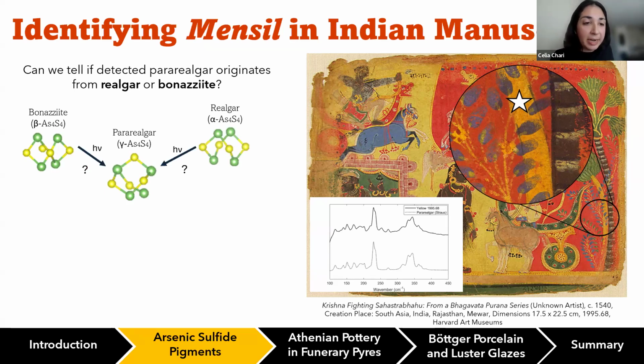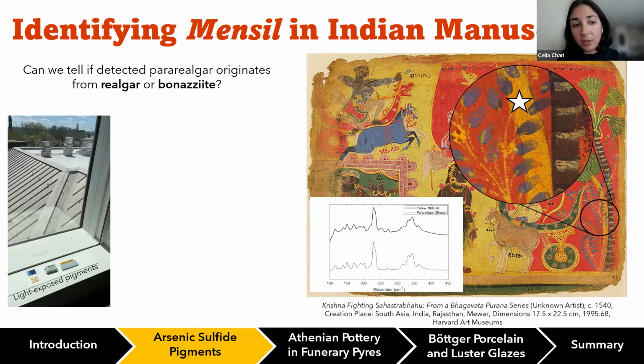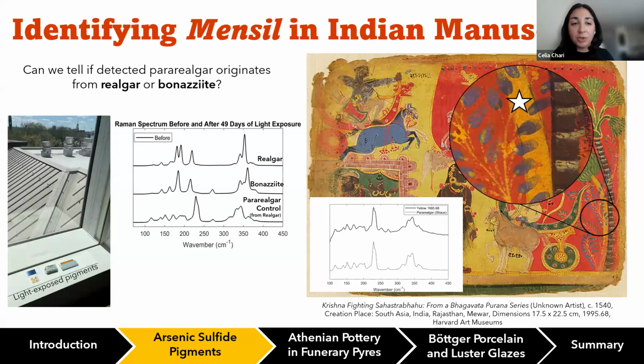To look into this, I carried out a few light exposure tests where I painted out different arsenic sulfides, exposed them to light from a window, also to different lasers, as you saw previously with the time-resolved Raman. And one thing that I noticed is that you can actually track a difference between the para-realgars derived from realgar or bonazziite using Raman spectroscopy. So for example, in this graph, I have Raman spectra for realgar, bonazziite, and this is just a control of para-realgar that I know has derived from realgar.